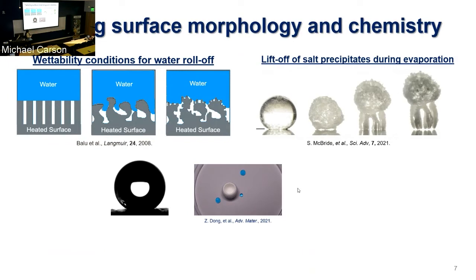There's also really interesting behavior with the salt itself. If these modified surfaces are subjected to a temperature gradient, what you find is that the salt crystals start to form these legs. And over time, those legs grow long enough that the salt crystal essentially ejects itself from the surface. So now you're not only preventing the water droplets from sticking to the surface, but even if any salt does form on your surface, it is going to eject itself from that surface because you've performed the surface modification. So these are really interesting things that have come out of the desalination world, but you could apply this to the design of heat exchangers, right? Where you really want to avoid salt precipitation and corrosion of any kind on those surfaces.